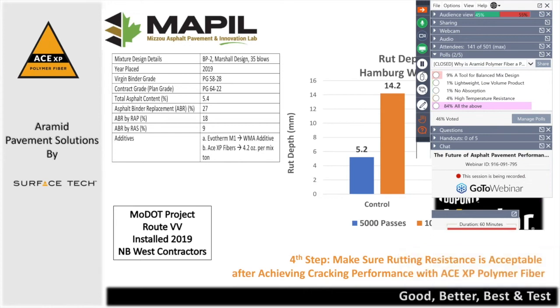Running Hamburg on that same mixture at 5,000 passes, the control was at 5.2, ACE was at 3.2. At 10,000 passes, the control failed. It was 14.2, and look where the ACE is. It's 4.8. Now, we didn't run it all the way out to 20,000 because all they expected for that rural road was really 5,000, because it's a 58-28, okay? But we actually made that 58-28 perform much, much better from a rutting perspective. Plus, we got 50% cracking.